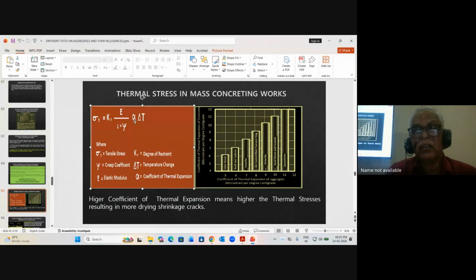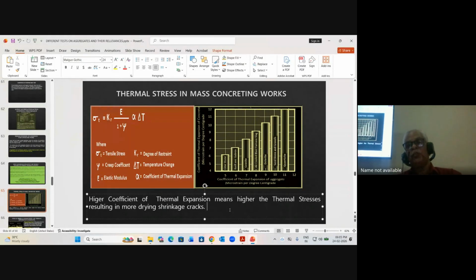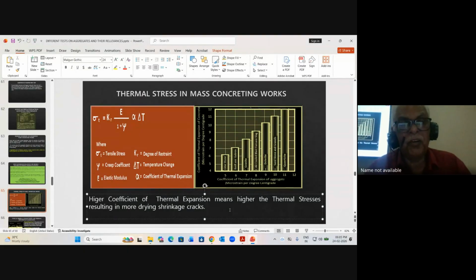Higher coefficient of thermal expansion means higher thermal stresses, resulting in more drying shrinkage cracks, while a lesser coefficient means lesser thermal stresses. So the most common problem in mass concrete work is the expansion and cracking due to drying shrinkage.